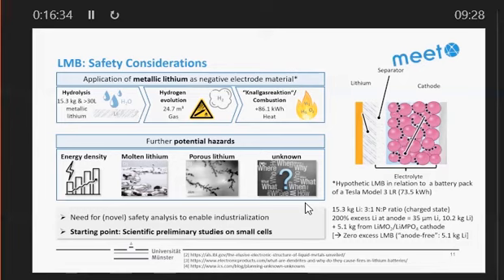Actually, a lot of papers say it's a great advantage that the density is low. It's not, because then the volumetric energy density is not great. This includes a 200% excess of lithium compensating for losses during cycling. If you took a zero-excess lithium metal battery, a so-called anode-free system, then 5.1 kilograms would remain. So still an enormous amount of lithium. Some of you who are chemists might be thinking, oh, so much lithium under my seat, so much reactive alkali metal. But this is the truth if we would work with lithium metal batteries.